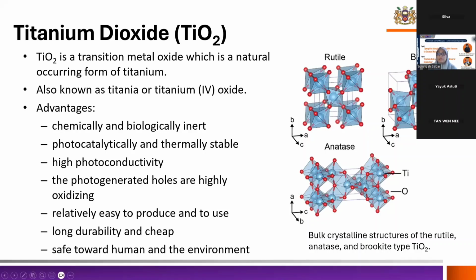So there are 3 types of crystal structure of titanium dioxide known so far, which are rutile, brookite, and anatase. The most widely used type of titanium dioxide is the anatase phase, because anatase is stable. It has a high photoconductivity and so on. While the least used type of titanium dioxide is the brookite type because of its complex structure and also unstable.